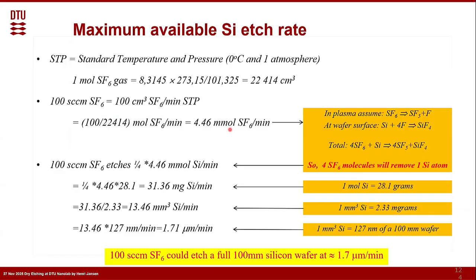But now in a plasma. Now let's assume a very, let's call it a perfect plasma. And we assume that all the SF6 which comes in is broken down into SF5 and F radicals. And we assume that at the surface, silicon will react with 4 fluor radicals to create our silicon tetrafluoride. It's really not a bad assumption, you will see it directly. So that means in total, we need 4 SF6 molecules to create 1 silicon tetrafluoride. So 4 SF6 molecules will remove 1 silicon atom.